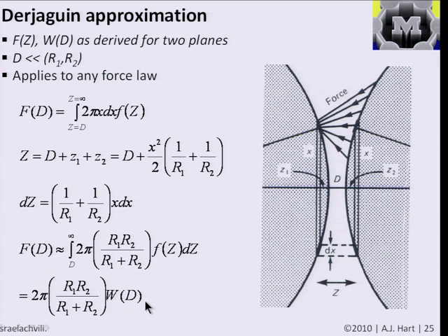And where this becomes really useful is that when we measure these energies experimentally, it's typically easy to measure the interaction between two curved surfaces. So you can create curves of materials much more easily than you can create and quantify very flat surfaces of materials and guarantee that they're separated very accurately at these very small scales. So by this approximation, we can relate the force as a function of separation for two curved surfaces, F of D here, to a factor that corresponds to the geometry of the two curved surfaces and the interaction energy between two planes.